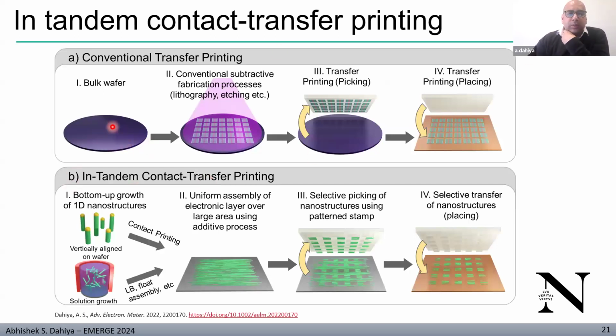So transfer printing, as I told, we have a bulk wafer. You do lithography, and then you bring your stamp and pick and place. In in-tandem contact transfer, what are the advantages? That you can use a wider variety of nanomaterials. So for example, bottom-up grown materials can also be used in this approach. So first you make an electronic layer, for example by contact printing, as I showed, all over the area. And then you can bring a stamp made by a standard molding process to pick and place selectively wherever you want. In this case, the lithography will be done only one time to make the master mold, to have a master template, and then the stamp can be fabricated without lithography every time using that master template. So that's the advantage of in-tandem contact transfer printing.